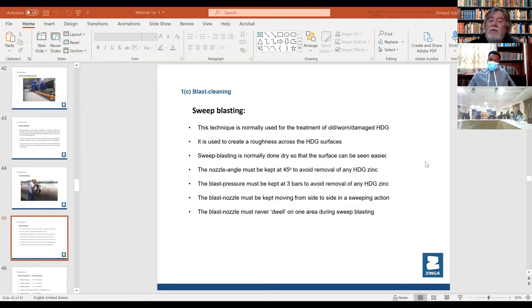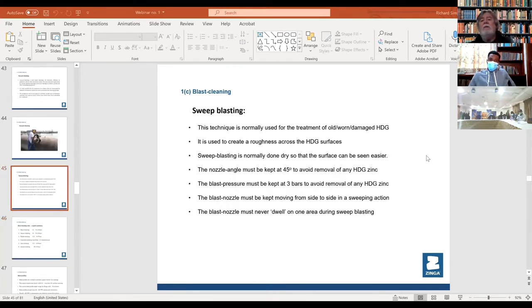Sweep blasting. This is another technique. I don't think we get photographs of it. No, we don't. When you sweep blast, when you have to repair old galvanizing on anything, towers and tanks, anything where they've been galvanized 40 years ago, 60 years ago, and around the world, there's literally hundreds of thousands of power pylons. These lines across the railways that carry the power lines for the train. There's hundreds of thousands of those galvanized structures beginning to get back down to bare metal because the zinc's worn away. So on a project like that, when you sweep blast, you don't blast at 6 bars. You reduce your blast pressure to 3 bars, and then you're sweeping from side to side fast. So all you're doing is breaking the surface to make it rough, but you're not removing the existing zinc that's still there because you want to retain that zinc.